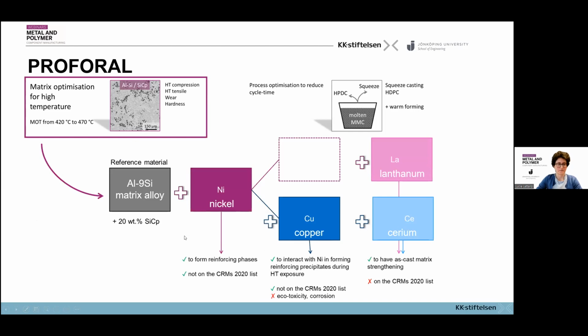So we started with changing the matrix alloy, and we decided to look into different possibilities of alloying elements to improve the mechanical performance at elevated temperature. So the first choice was nickel, because it's known to form reinforcing phases that are thermally stable in aluminum silicon alloys. And thinking of sustainability, nickel is not on the critical raw material list.